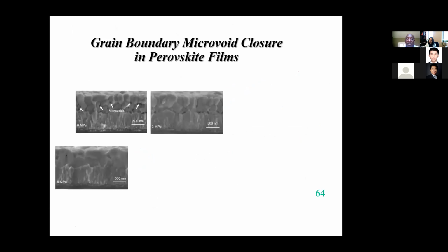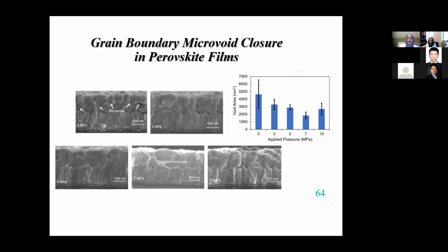So what interests me in these systems is that as you apply pressure, you close microvoids in these structures, and you increase the contacts of asperities in ways that enable more favorable pathways for the flow of charges to the electrodes. And so as we increase our pressure from 3 to 5 to 7 MPa, what you find is you reduce your microvoids, you enable more contact pathways. But when you go to 10 MPa pressure, you increase your microvoids because you start cracking the material.